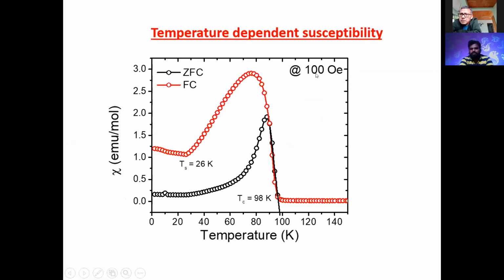Temperature dependent susceptibility clearly shows that at high temperature the sample shows paramagnetic nature. Whenever temperature decreases, at a certain point both the ZFC and FC curves suddenly increase. That temperature is the Curie temperature, and that region is called the ferromagnetic transition.